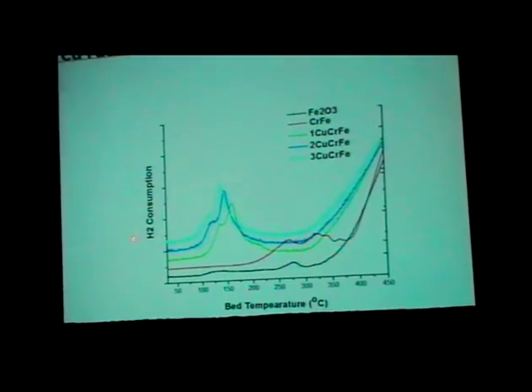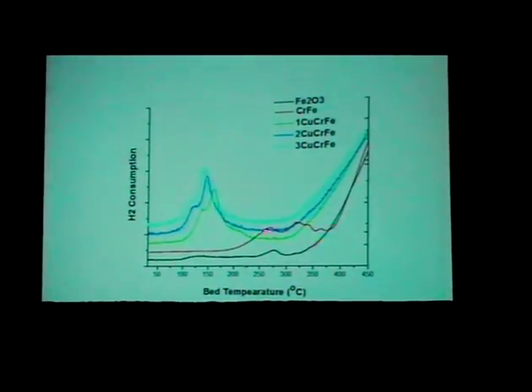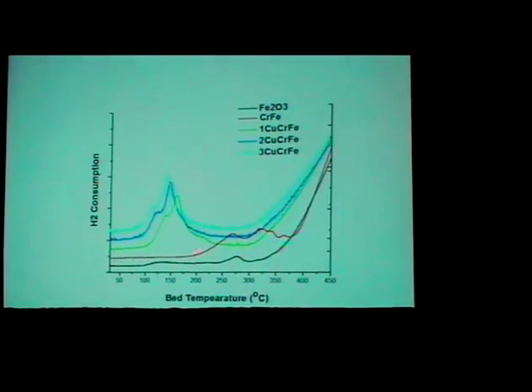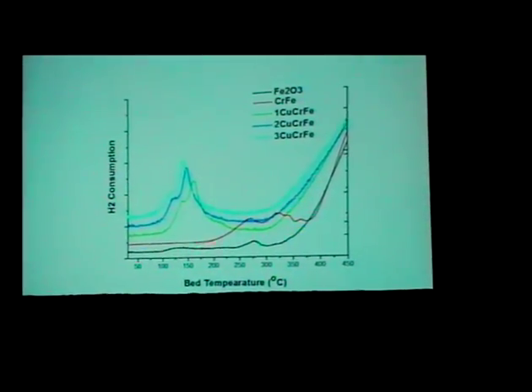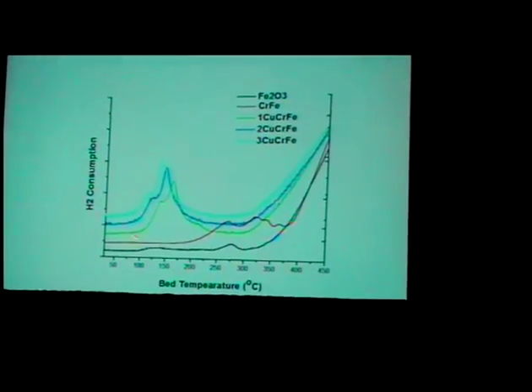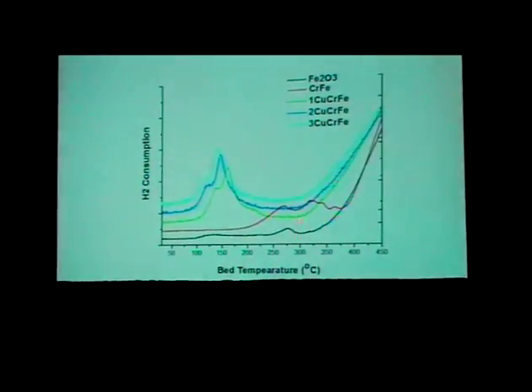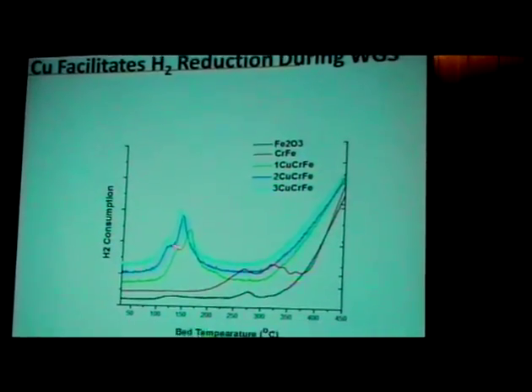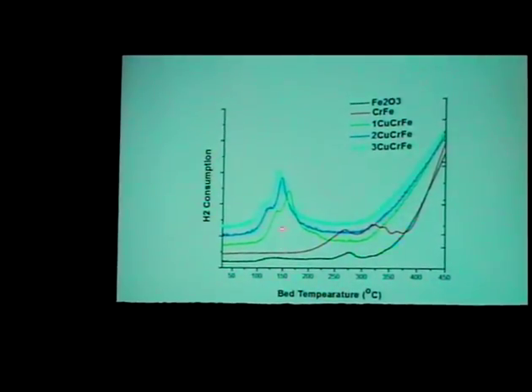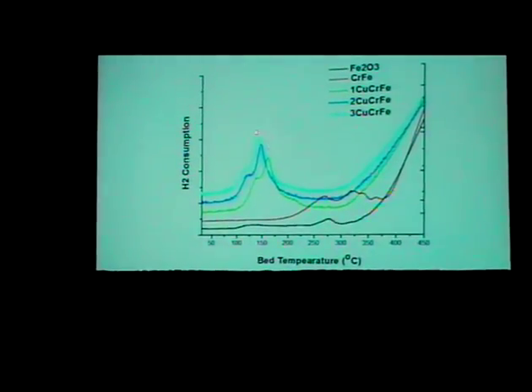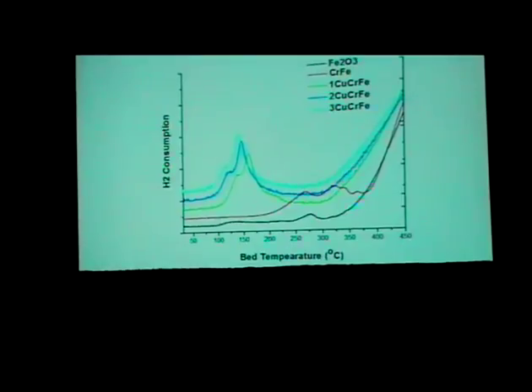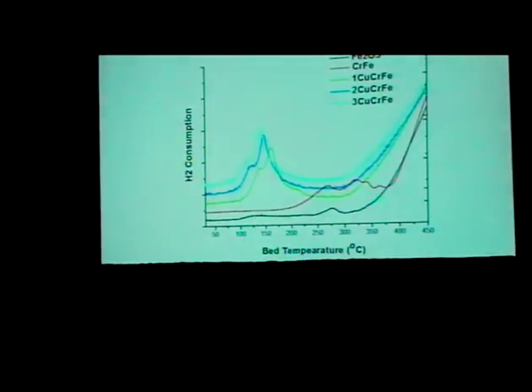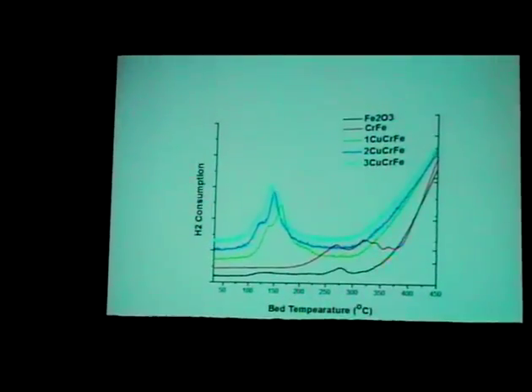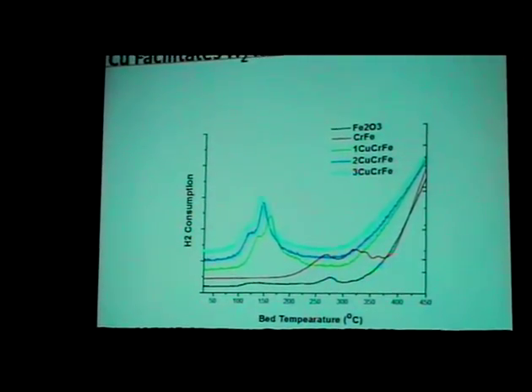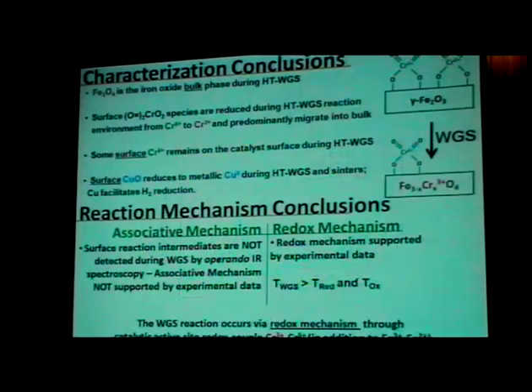I'm showing you here the hydrogen temperature programmed reduction of the catalyst. This is iron. At the bottom, this is what happens when you add chromium, because of the reduction properties. This is what happens when you have copper. And these catalysts are treated under water gas shift reaction conditions, so not fresh catalysts, they are active. And you can see the tremendous ability of the copper to reduce, and the more you add, the more you have the reduction of the catalyst. And so copper is dissociating hydrogen and enhancing the spillover of hydrogen to further activate and create the redox on the chromium catalyst for the water gas shift reaction.